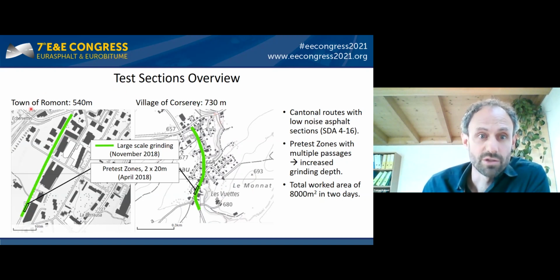On this slide, I show you an overview of the 2 test sections I'm talking about today. The first one in the town of Romont with a length of 500 meters in an industrial district, rather high traffic. The second one in the village of Corserey, 700 meters in length, less traffic, but much more agricultural activity, which usually contributes to the clogging. After successful pre-tests in 2 times 20 meters zones in April 2018, we processed the entire road in November 2018 and a total of 8,000 square meters in 2 days.